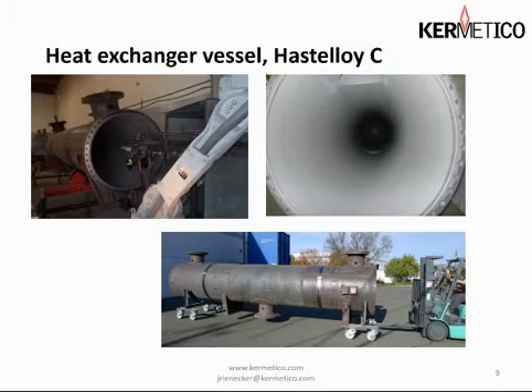This is an example of one - it's a heat exchanger shell. We've coated the ID with 10 thousandths of Hastelloy C to prevent attack from acid-containing fluids: hydrochloric, sulfuric, naphthenic, carbonic - I mean, you name it, they got it. It's all bad. This coating works very well, it's protected the vessels. We have some now going on 5 years or slightly longer. You get an idea of the scale of this vessel by comparing it to a 5,000-pound fork truck - the thing is huge.